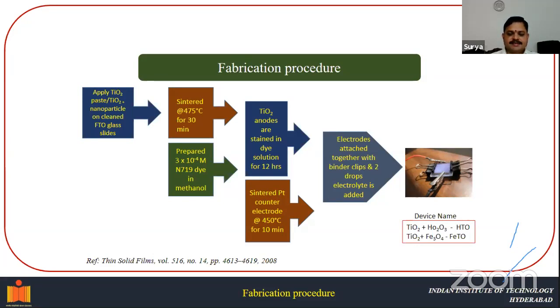So now, how to fabricate dye-sensitized solar cells? In our work, we have developed different devices: titanium dioxide plus holmium oxide, which we call HTO, meaning holmium titanium dioxide based device, and titanium dioxide plus Fe3O4, FeTO. Before, we developed three different devices: the parent titanium dioxide device, the HTO device, and the FeTO device.